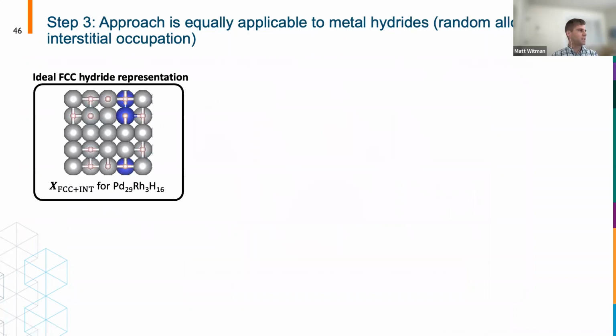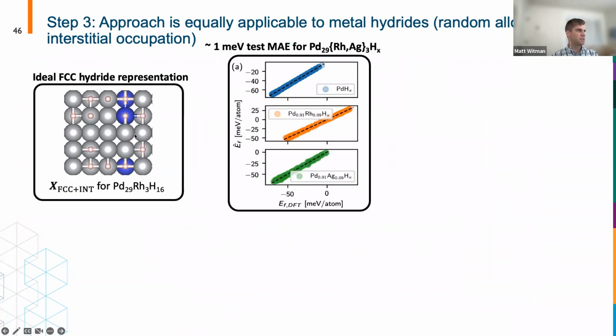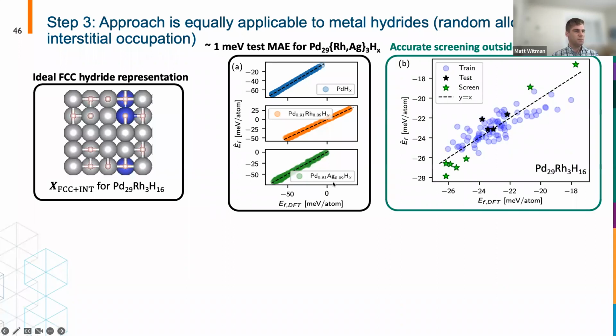So finally, we redid this, now demonstrating it for hydrides. You can have the ideal representation for a hydride phase. Again, we can validate these models. They're extremely accurate based on these ideal representations for predicting the hydrogen adsorption landscape in these palladium-substituted systems. And again, these green points are materials that we've screened outside the original DFT data set, which we've revalidated to show that the model accurately captures lower and higher energy configurations than anything that's been trained on.